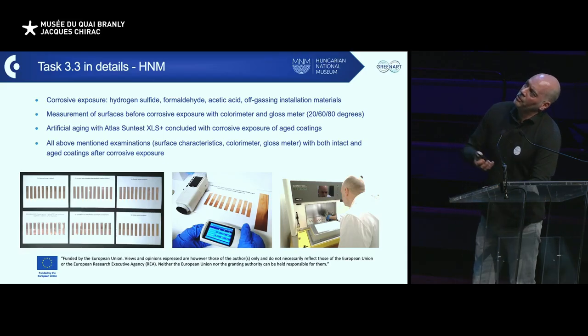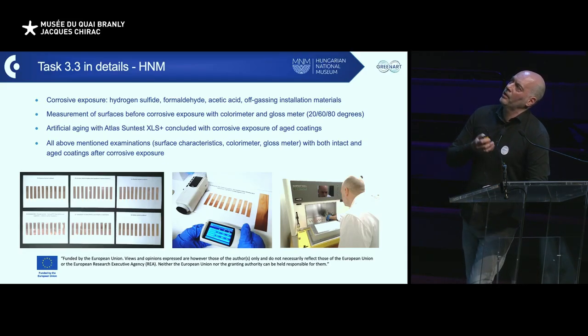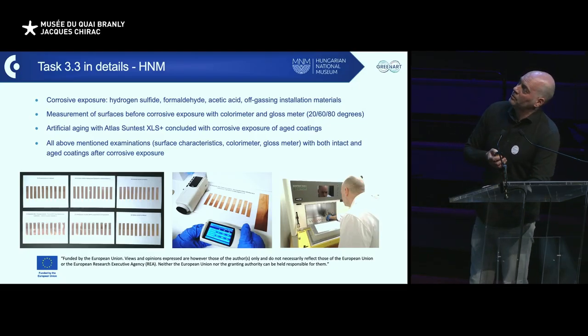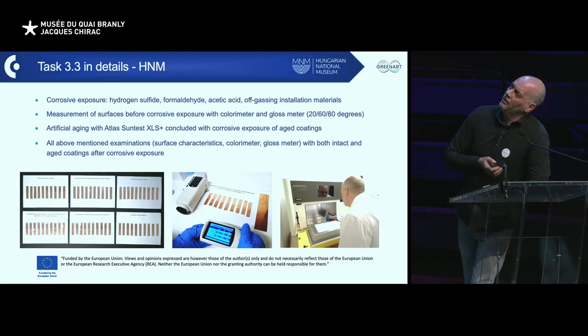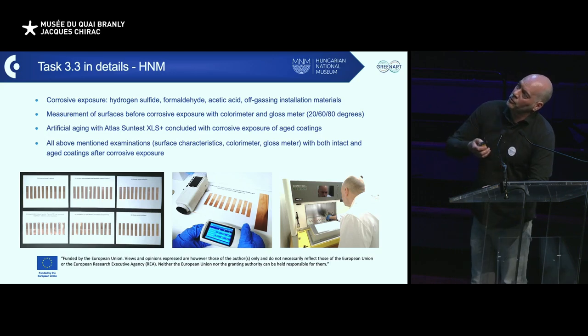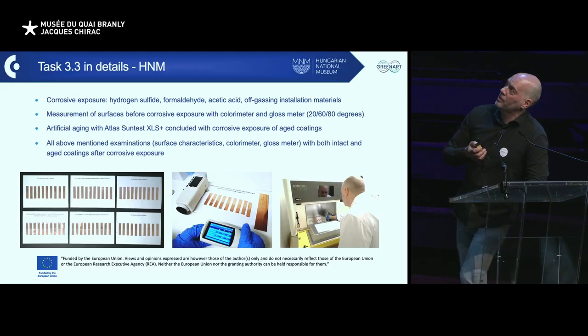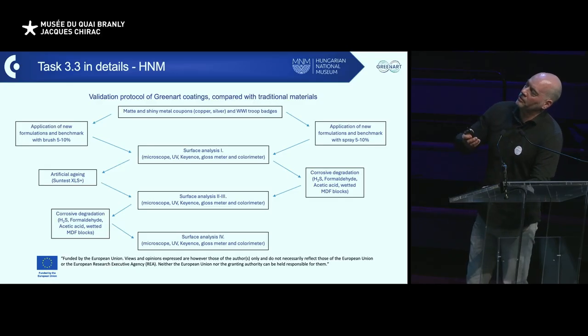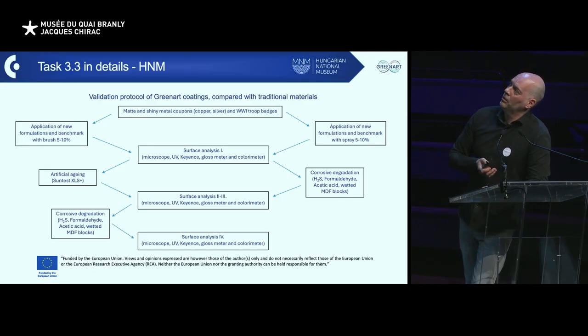documentation, and we will use some corrosive exposure with hydrogen sulfide, formaldehyde, and acetic acid, which are the most common off-gassing materials in our museum environment, which is not so good, but that's the reality. And we will measure with a colorimeter and glossimeter, and we will also use some artificial aging in our new artificial aging chamber, and we will do all the mentioned examinations with both intact and aged coatings. This is the schematic scheme of the validation protocol we'll use, just as I explained to you before.